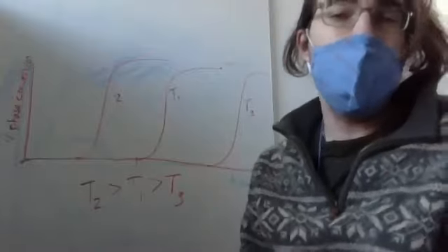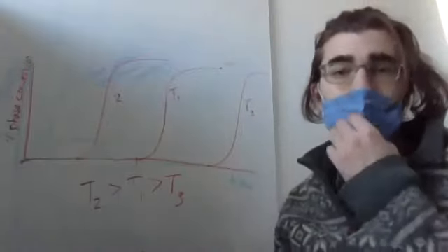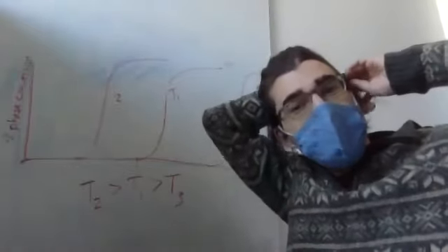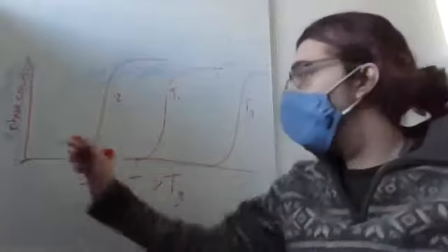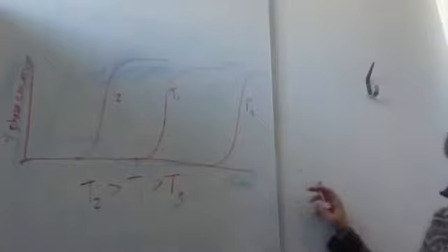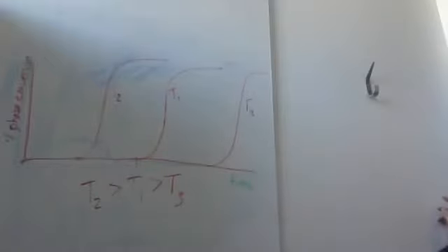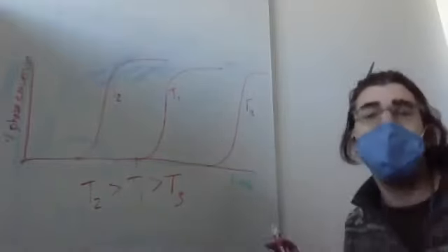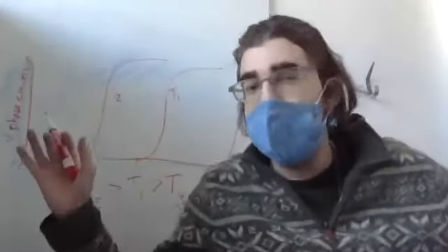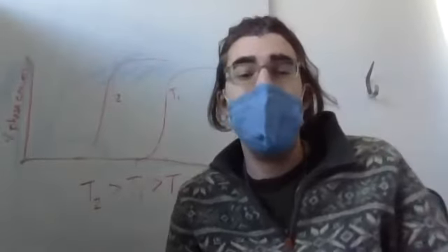and if we go to a temperature even lower than that, a temperature so low that diffusion basically doesn't occur at all, right? What's going to happen? We're going to wait forever and ever and ever. We're going to be still waiting for diffusion to occur, for the atoms to grow to get to this huge crystal size where they're stable, and recrystallization or the phase change will never occur.